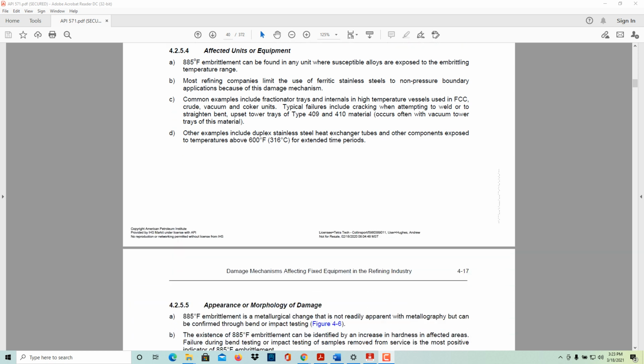Affected units and equipment. 885 embrittlement can be found in any unit where susceptible alloys are exposed to the embrittlement temperature range. Most refining companies limit the use of ferritic stainless steel to non-pressure boundary applications because of this damage mechanism. Common examples include fractionator trays and internals in high temperature vessels used in FCC, crude, vacuum, and coker units. Typical failures include cracking when attempting to weld or to straighten bent, upset tower trays of type 409 and 410 materials. This occurs often in the vacuum tower trays of this material.